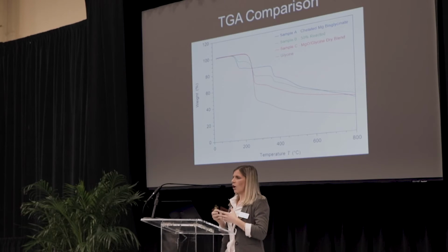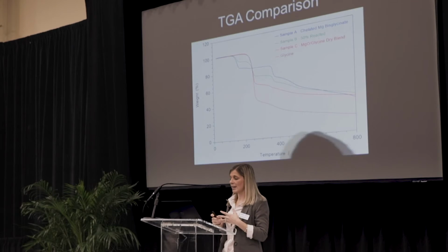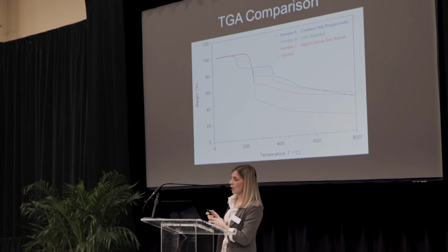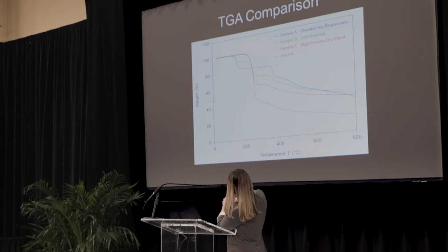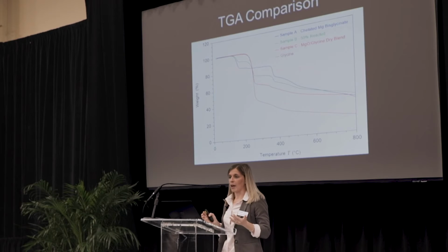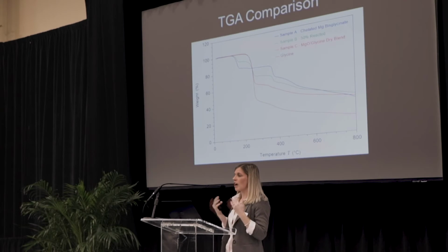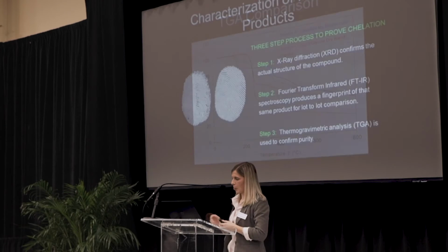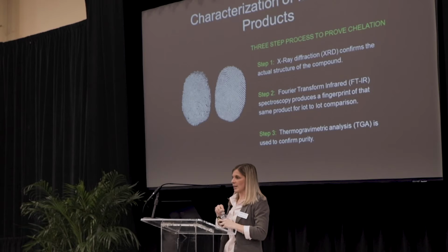And the first thing you can notice is they just all have different profiles, right? They all look very different. So again, this is sort of a fingerprint for this compound. I've also put glycine up on here in the dark red. And one key thing that you can see is that sample B, which does contain unreacted glycine, and sample C, which also contains unreacted glycine, both overlap in this region. However, sample A, which is the fully chelated magnesium bisglycinate, is flat throughout that region, indicating that we don't have any unreacted glycine present in the sample. So again, this is just another check for the purity of our compounds. So again, through this 3-step process, we are putting the data behind these products to fully prove chelation.